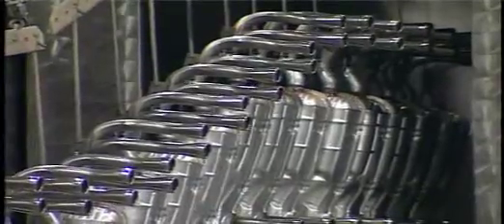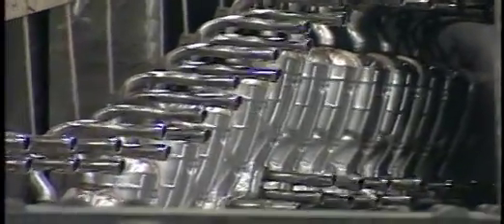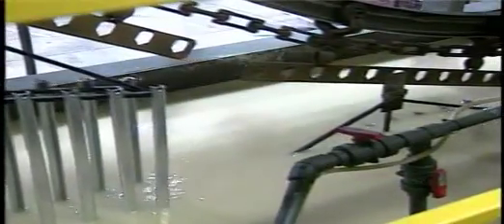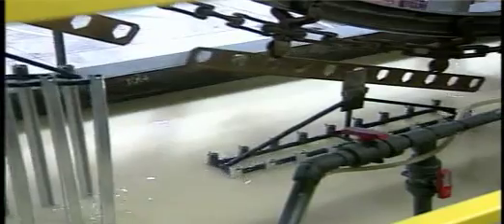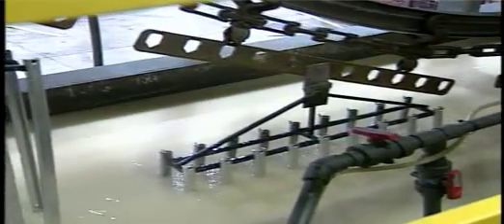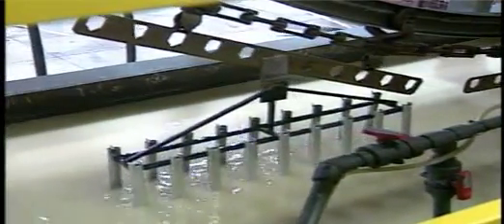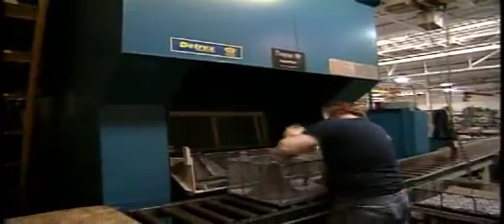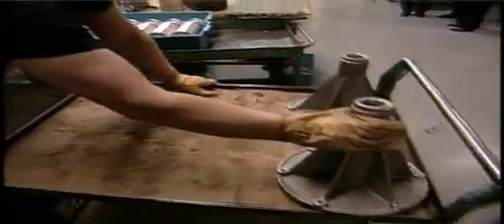Preparation of the surface to be coated is necessary to ensure proper adhesion between the coating and the surface. Typically, metal surfaces are cleaned with a detergent or aqueous alkaline solution in order to remove dirt, oil, grease, and other contaminants. In some cases, organic degreasers may be used to remove heavy machine grease and milling agents. In some industries, such as transportation, manufacturing, and refinishing, a solvent wipe may be used after the initial cleaning step to remove any traces of oil and grease that might remain.